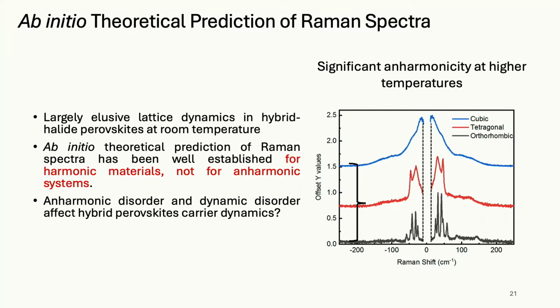And then look at room temperature. What the heck is this? Do you see? You get response at every frequency. So that is frustrating. And people would say, oh, that's because of the disorder of the molecule. It's not. We did the same thing with cesium lead iodide, where it's not a molecule, it's just an atom. And you get this same diffuse, almost structureless blob. So that was extremely interesting to us.